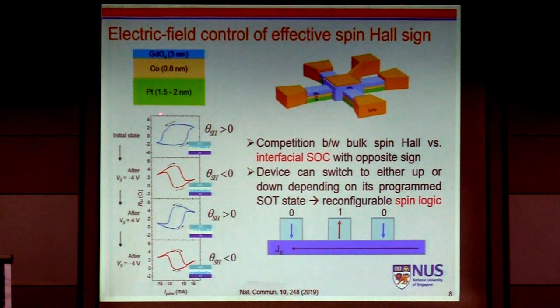This is again a very conventional positive spin Hall system, platinum, cobalt. Then we put gadolinium oxide on top, and by gating this, we can push oxygen into the cobalt. Once we apply a positive voltage, we can pull this oxygen back in a reversible way. By doing this, we found the spin Hall angle changes from positive to negative, positive to negative, with almost equal magnitude. So we were able to repeat our earlier experiment now in a single device and show feasibility. We can program those directions by gating. This gives an opportunity to think about FPGA types of applications in spin logic.